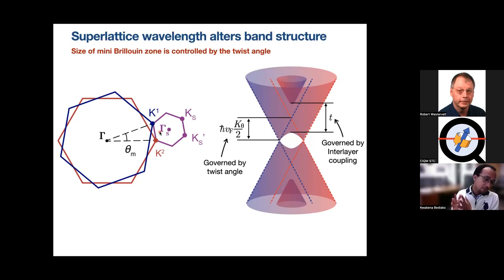And so an important point here is that the point of intersection between, let's say we had two graphene layers, the two sets of cones, is controlled by the twist angle, right? And the size of the hybridization gap that is opened as a result is governed by the extent of interlayer coupling or interlayer tunneling. Now, what I've shown here is just for two of the six K points of